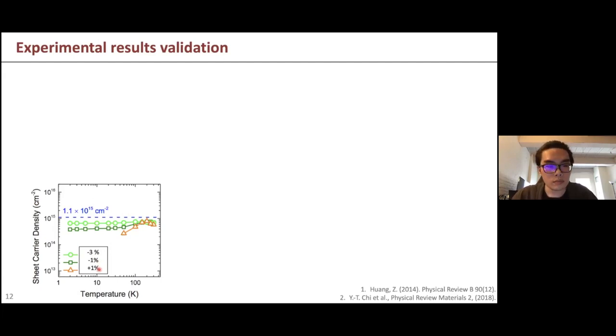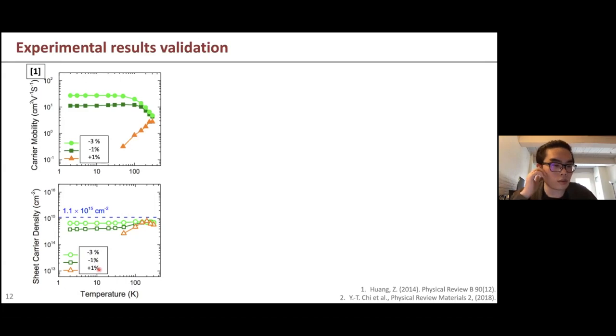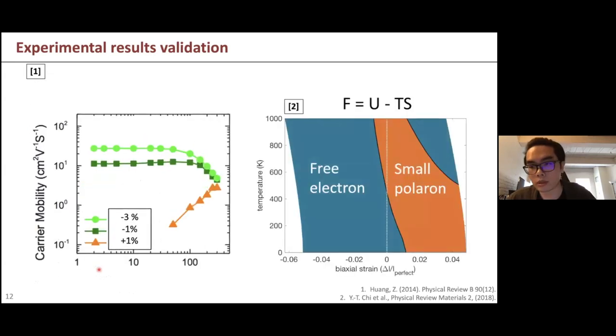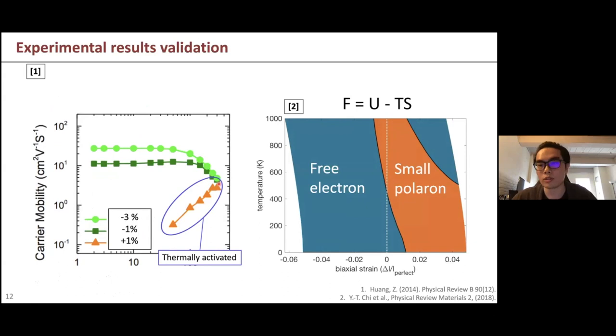By conducting the Hall measurement, they can get the carrier mobility of the thin film with temperature in all three samples. If we just enlarge this and compare with my predominance diagram, let's look at the one with tension, which is the orange triangle here. As you can see, they are very different. And this one is very temperature sensitive. Here I call it thermally activated.